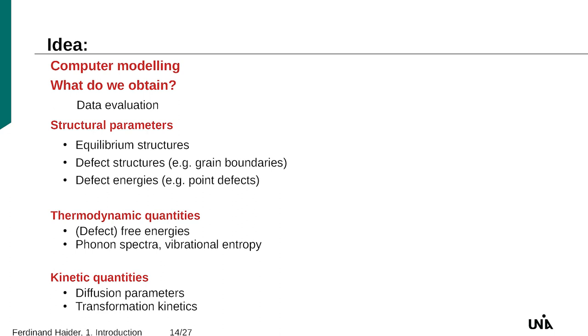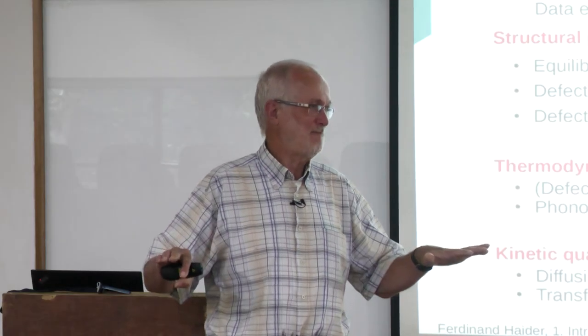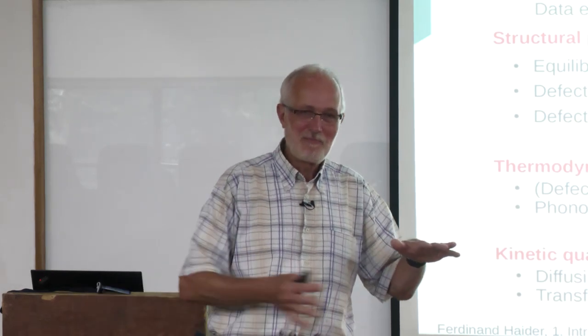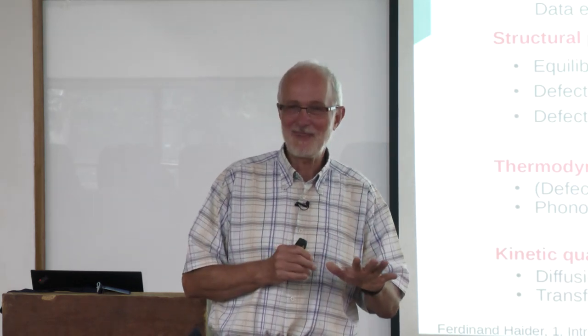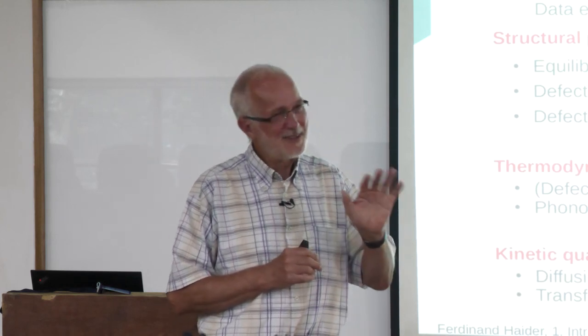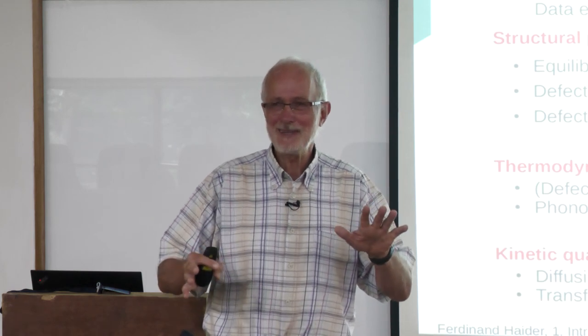Then, where DFT has a very hard time, but which is easy in molecular dynamics, you can get thermodynamic quantities. The reason is DFT basically is at zero Kelvin, and more or less artificially you can plug in temperature to it. As I said, temperature is a complicated thing. In MD, you don't get the temperature for free, but at a low price, I would say.